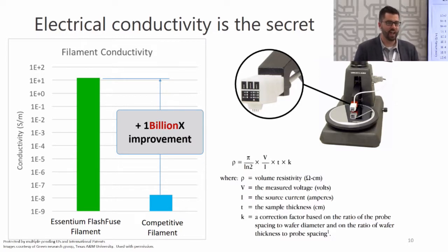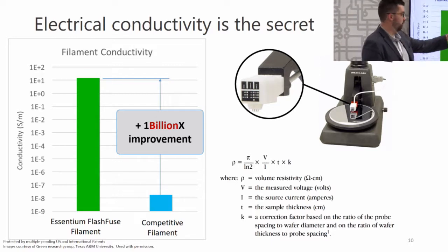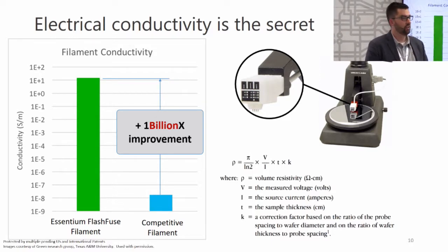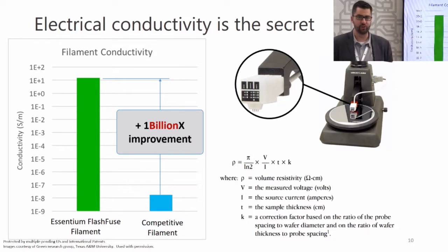Let me say that again. We're 9 orders of magnitude more electrically conductive than the next closest conductive polymer that's available on the market. We've used 4-point probe tests, we've measured printed parts, we've measured filament, and this is why our technology works, because the electrical conductivity is so much higher.